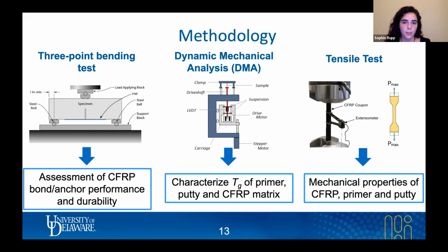There will also be dynamic mechanical analysis tests completed, or DMA for short, in which we will apply a cyclic load to the sample that's being tested, which in this case will be the neat epoxy and the putty epoxy. The cyclic load is applied as the temperature is increased, and this is so that we can characterize the glass transition temperature of the samples, or Tg for short. The glass transition temperature is a characterization of when the sample goes from being a glass-like state to a plastic or a rubbery state. And the reason that this is important information to have is so that we know the upper service limit temperature of the material.